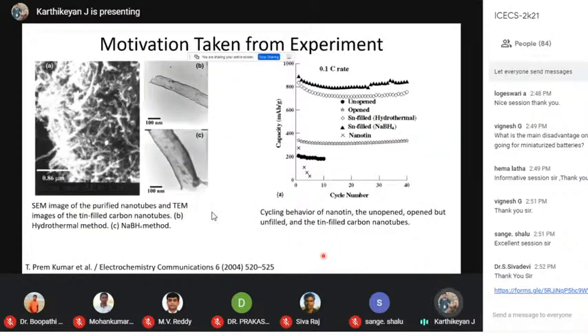So as I told you, today I'm going to present two works, both motivated from experiments. Already I talked about the problems associated with tin or silicon, which are alloying type materials. Also the problems associated with the carbon type materials. The carbon type materials have a low specific capacity, but they have very good electronic conductivity. There are many good aspects, but capacity is low. But on the other side, silicon and tin have a very good specific capacity. The problem is they don't have good electronic conductivity, and they suffer pulverization and huge volume change. So these we don't want.